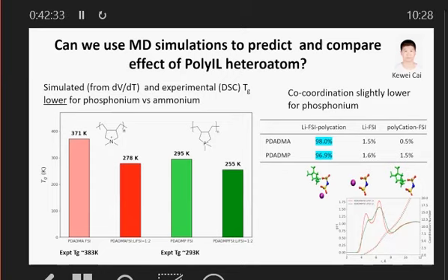Again, we think we can trust the data because we have a similar TG to what we measure. And then in the 1 to 2 system with FSI, what he found was that the TG doesn't go down as much in the phosphonium system, but it does go down. On the right-hand side, we see, again, this coordination is not that different. It's a little bit lower.